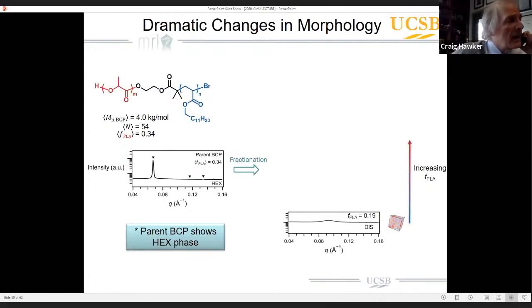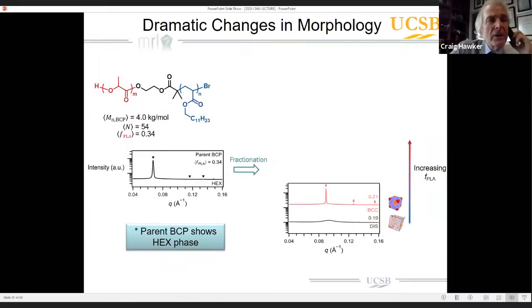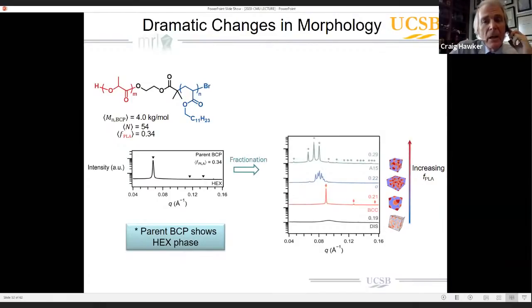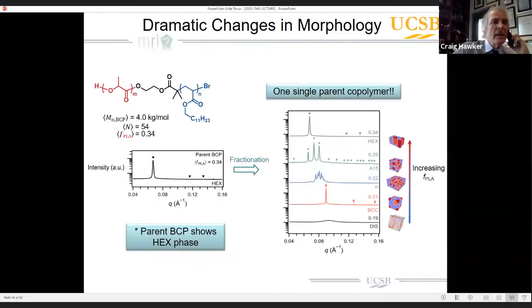Then you go and examine your fractions. The early fractions are disordered. We then have fractions that are around about 21% that clearly are BCC. And then lo and behold, the new things start to pop up. Now, at approximately 22%, we are starting to see what's called a sigma phase. We then observe the A15 phase, hex, and then lamella. So from this one single parent copolymer using a fairly simple chromatography separation procedure, we're getting a library of materials that we can start to observe a really complete morphology picture.